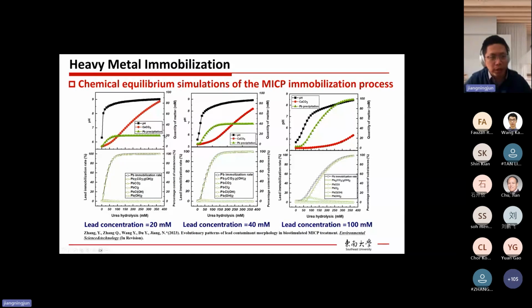Okay, then we further performed a chemical equilibrium simulation using the software Visual MINTEQ to simulate the MICP immobilization process. So as you can see here, the horizontal axis shows the amount of urea hydrolyzed, and the vertical axis shows pH and the quantity of different precipitation species. Then when the lead concentration is 20 millimole, we can see the pH increases very quickly with the amount of hydrolyzed urea. And initially, we can see the lead precipitation happens, followed by the calcium precipitation. Then, if we have more lead in the system, firstly, the increase in pH is delayed. And secondly, we have more lead precipitation at the first stage, followed by the calcium.